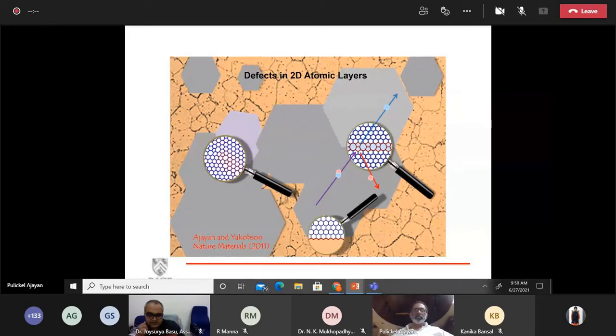I was saying that CVD growth produces defects, and the defects in some of these 2D materials are also quite interesting. For example, if you look at graphene, which is a really single atomic 2D layer system, it's a hexagonal honeycomb lattice. One would wonder what the grain boundaries would look like. And it seems that these grain boundaries are made from topological defects like the 5-7 membered rings. People call it the Stone-Wales defect in carbon. And it has been shown that these defects are really present at these grain boundaries. And even the electron transport through these grain boundaries depends on how exactly the grain boundaries are made from these defects. So there's a lot of detail that could be fascinating in some of these atomically thin materials.